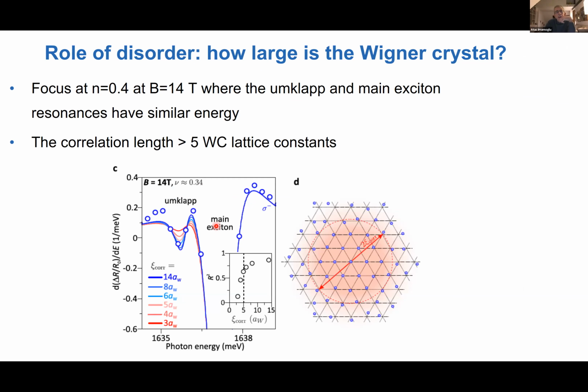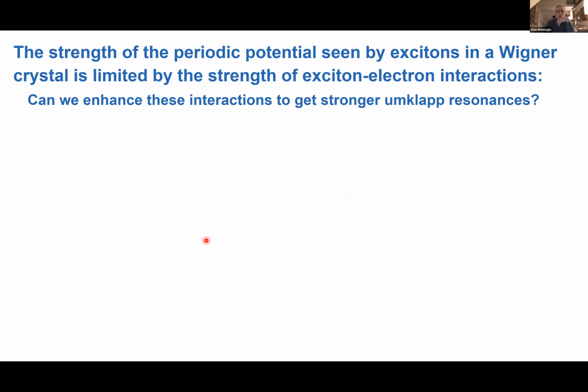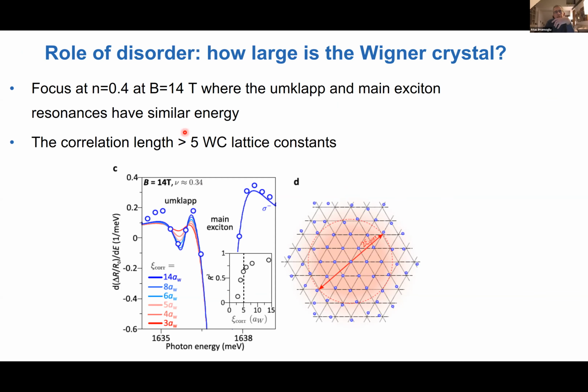So, this is nice, because now that we have an actual Umklapp resonance that we can see and identify its center frequency and line width precisely, what we did is we tried to look at the effect of disorder and extract its magnitude from the line width of the Umklapp peak. And from this, we were able to determine a reasonable estimate of the correlation length, which we believe is larger than 5 lattice constants. So if you are to be precise, all we can say is that we have Wigner crystallites, which have about 50 electrons or so, maybe more, but we cannot say based on the spectroscopic signatures we have.